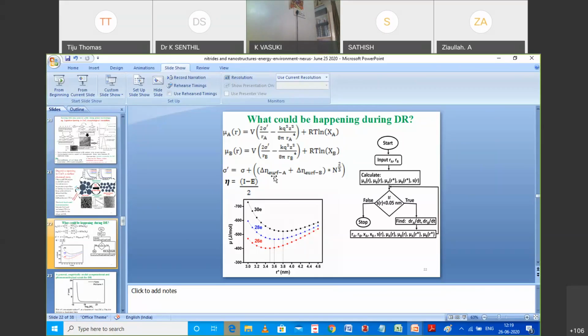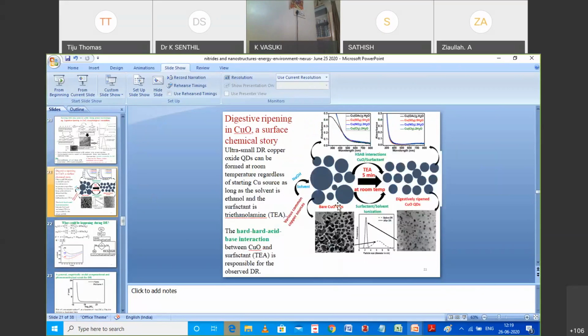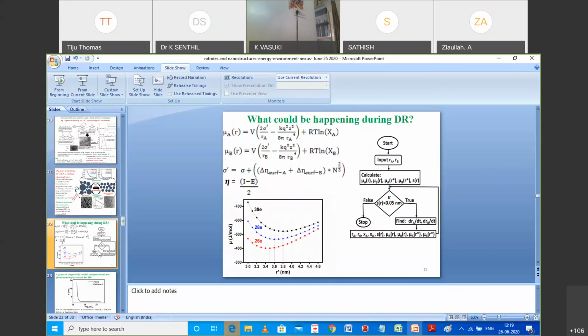And then with the set of these four equations, we started seeing mu versus radius showing some kind of a minimum. And that is the reason for this collapse in particle sizes from what would otherwise be a jungle of particle sizes to a single particle size. So this is very exciting because there is nothing in this equation that requires you to believe that it should work only for oxides.